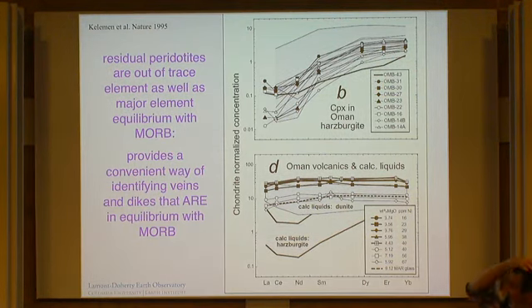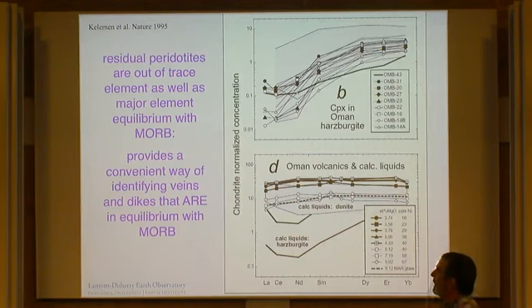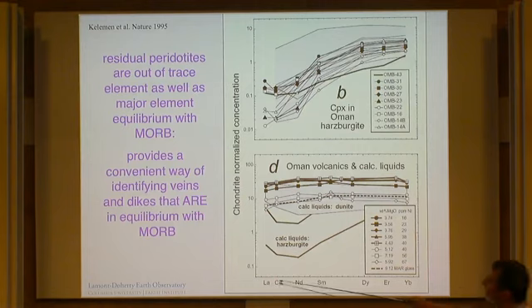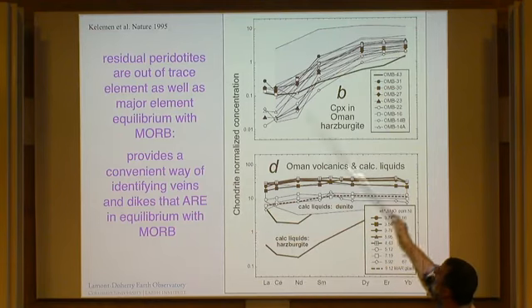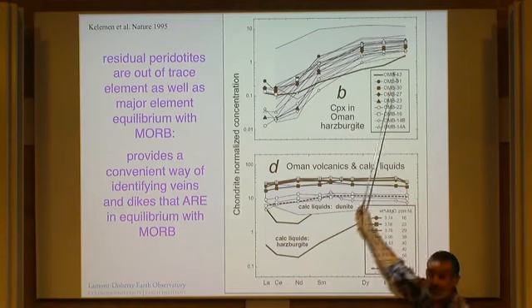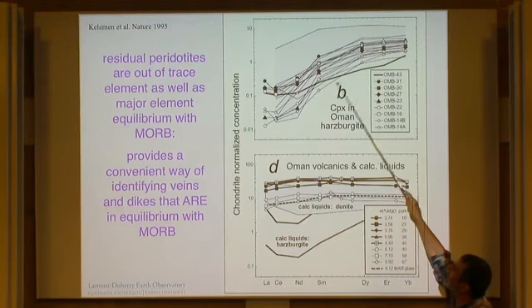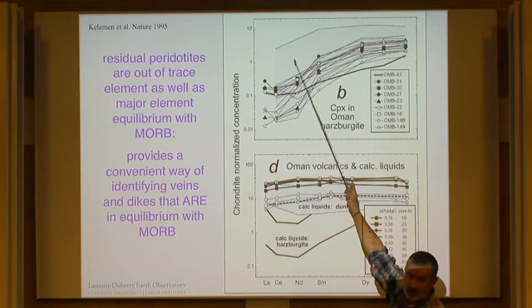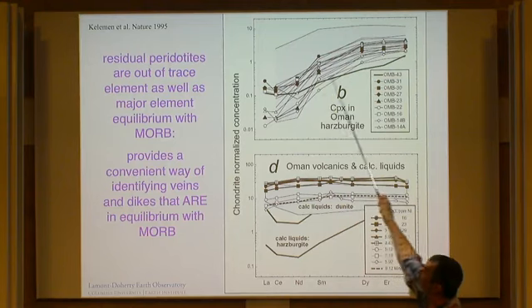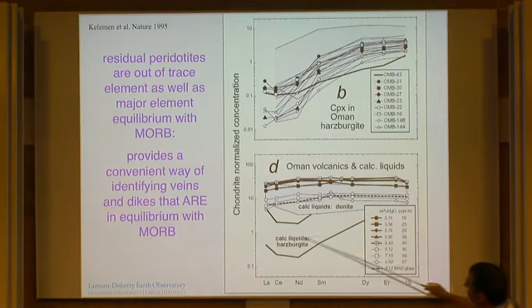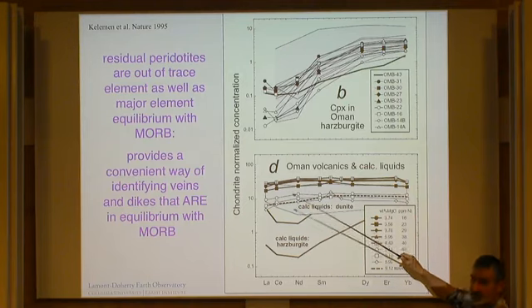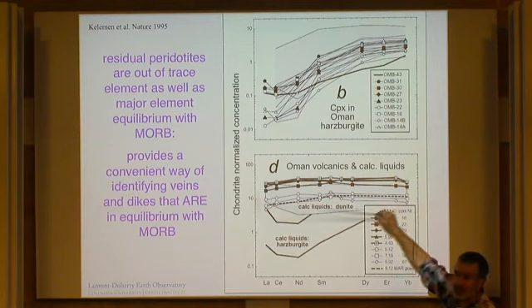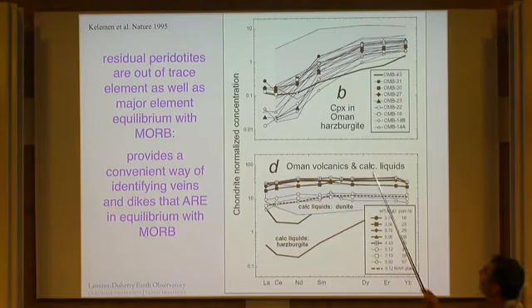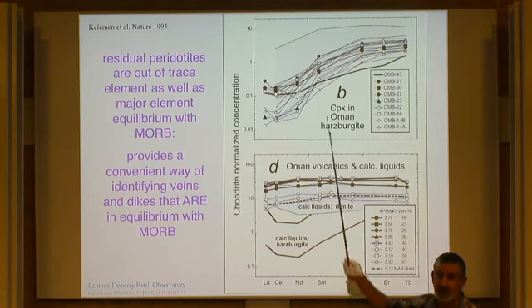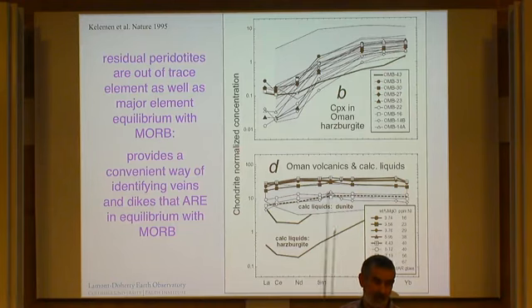So when we go to Oman, fortunately we find things that are pretty good analogies for what we dredge and drill from the mid-ocean ridges. For example, here are the rare earth elements, from lanthanum on, normalized to chondritic concentrations. We can measure little bits and scraps of clinopyroxene that we find in the residual mantle peridotites, and they're very strongly depleted in the light rare earth elements, just like the abyssal peridotites that comprise this gray field that are dredged from the ridges. If we calculate liquids in equilibrium with these, we get these kinds of compositions. And if we look at the lavas that form the crust, we get these compositions, and they're different by a factor of 20 or so. So we can say that the lavas that form the crust in Oman were not in equilibrium with the shallow mantle residue from which they were extracted, just like mid-ocean ridge basalts.